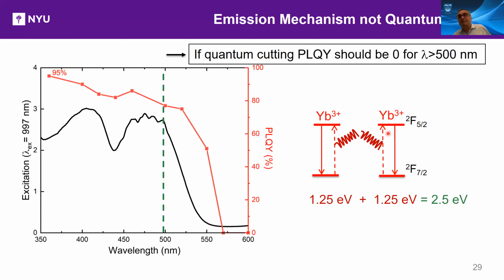So I talked about very high photoluminescence quantum yield. So the question is, is this quantum cutting? Unfortunately, I'm here to tell you that we have data to show that the emission mechanism in this particular case is not quantum cutting. At least there is a mechanism that is not quantum cutting contributing to the photoluminescence quantum yield.